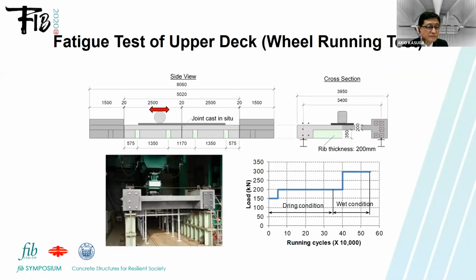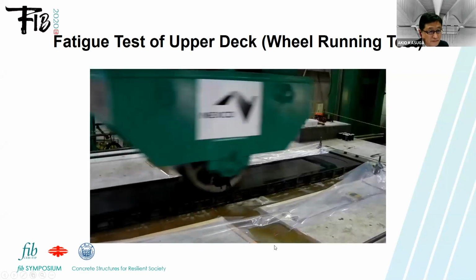And also, a highway company asked us to confirm the fatigue by using a wheel running like this. They have a regulation to check the durability of the slab from 150, 200, up to 300 kilonewton, about 500,000 times. From here, this is dry condition. From here, the wet condition is still needed to check the durability of this deck. So I hope this works well.